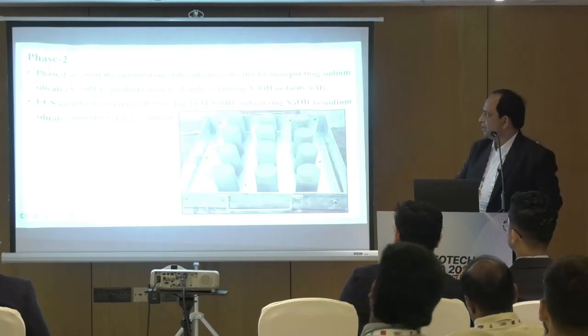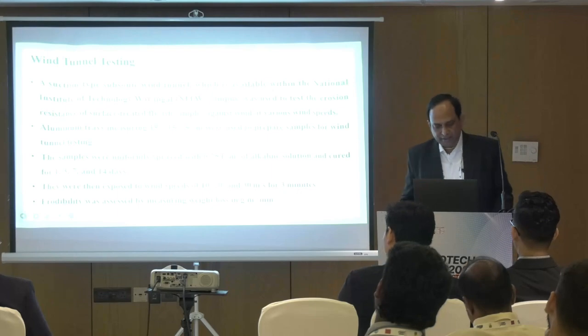In phase 1, as I have already mentioned, we prepared different samples for UCS with different molarities of NaOH, and of course we determined OMC and MDD. In the second phase, along with sodium hydroxide, we took sodium silicate with different proportions, as we have seen, 0.5, 1, 1.5, and of course 2. And here we had one wind tunnel at NIT Warangal. So we prepared the sample, kept it in the wind tunnel, and tested different velocities, 10 meters per second, 20, like this. We thought of checking this one.